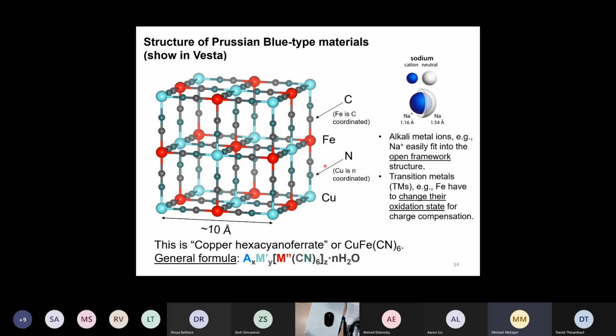So that's why we would call this a copper iron hexacyanoferrate, because the CN group here that spans this framework is also called a cyano group. And we basically always have 6 of them surrounding the individual atoms. So if we look, for example, at this copper atom here on the right side of the cube, you can see, first of all, it's coordinated with the nitrogen. And you can imagine, there's 1 here, 2, 3, 4, 5, and then there's the 6th one that we cannot see here. So the 6, of course, gives rise to this hexa number. And then cyanoferrate, because most of these materials use iron. And then copper is just an example that I chose here so that we have 2 distinct types of transition metals in this material.